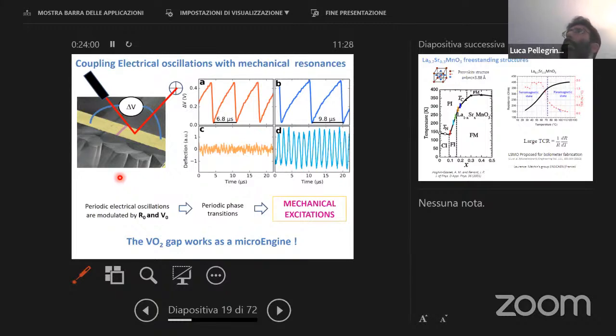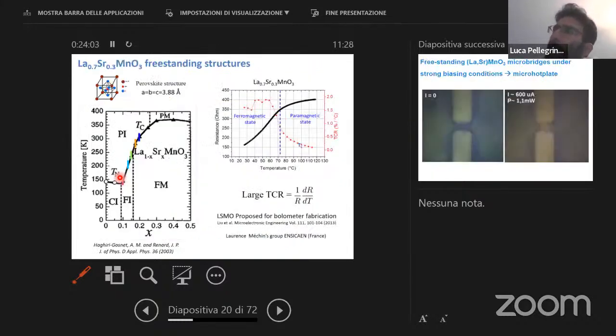but at the same time you have quite large force and power. We now change material, and we now move to manganese oxides. Manganites are quite famous oxides in the oxide panorama, because they have magnetic transitions, and this is the phase diagram of manganite with lanthanum and strontium. And depending on the lanthanum strontium stoichiometry, you have different behavior. Here you have paramagnetic and ferromagnetic metallic behavior, and in particular the 0.7/0.3 composition has this phase transition above room